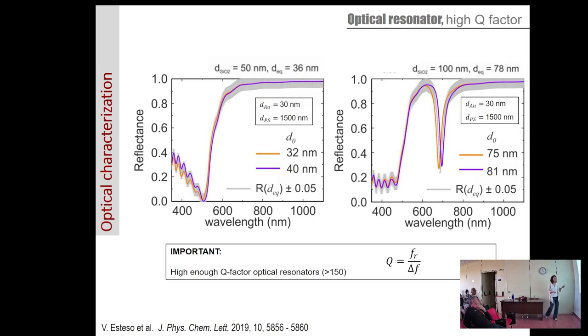Why is this important? Because the way we are going to extract the information is by fitting with a multilayer transfer matrix method, and then we are going to extract the thicknesses of the material. The thickness of the polystyrene layer is important for the buoyancy. Exactly, we were playing with that. So within the design, we needed to make sure that we were not just observing some floating effect or something like that.